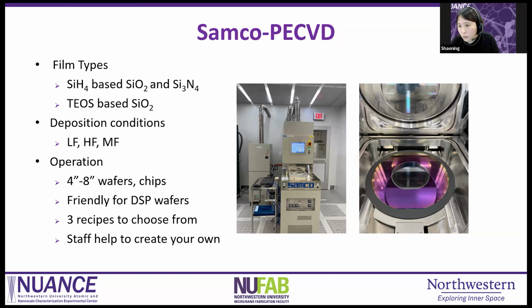Why do we introduce this one? Because it has some advantages, like it can provide a lower deposition temperature. Currently, we're working with the existing tool and silane-based. This silane-based process is around 300 to 350 degrees C. TEOS-based process is 250 C. And it also provides a little bit smoother surface and is a little bit more conformal. That means it has better step coverage if you have some etched structures on your wafer or some deep trenches. This one will give you better sidewall or corner coverage.